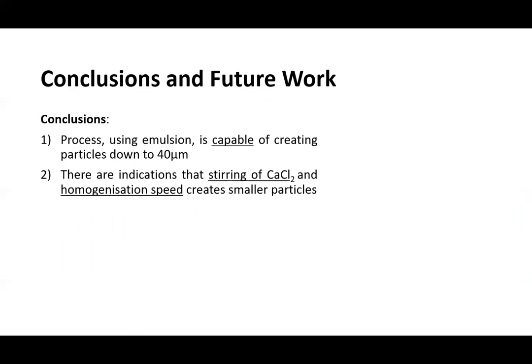Conclusions and future work. Conclusions: This process, using a double emulsion technique, is capable of creating particles down to 40 microns. There are indications that stirring of calcium chloride and homogenization speed creates smaller particles. Commercial applications using this process to create particles include sprays, creams, ingestibles and injectables.